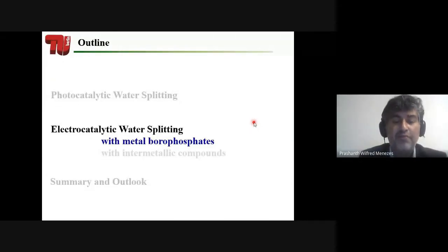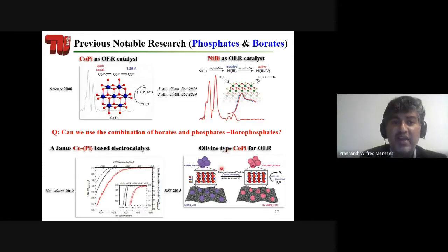Okay, so now I would like to introduce a couple of examples. First, I would like to show you that we have discovered a new class of materials for water splitting, called metal borophosphate. Why did we start to work on this topic? Because a study from Harvard and Stanford showed that cobalt phosphates can be very good catalysts for oxygen evolution reaction. They also came up with another report that nickel borate could be a better catalyst for oxygen evolution reaction. Similarly, a group from Korea also showed that crystalline cobalt phosphates are very good catalysts for oxygen evolution reaction. And in the meantime, a group from France also came out with a report that they could be used for hydrogen and also oxygen evolution reaction.